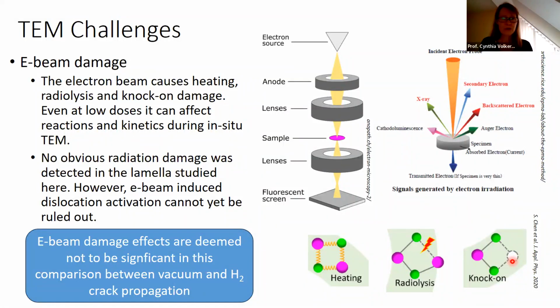They typically produce damage that is characteristic, and from our experience, we know what damage looks like. And I'm going to just say here, we saw no obvious evidence of the effect of electron beam damage on our observations. So to first order, we're going to say it's not significant here. I believe to first order this is correct, but it is an assumption at the moment that's based on our experience.